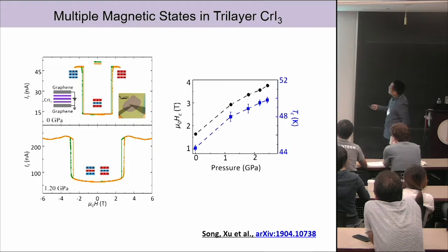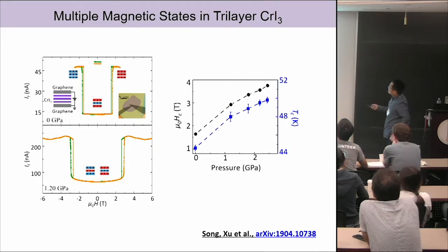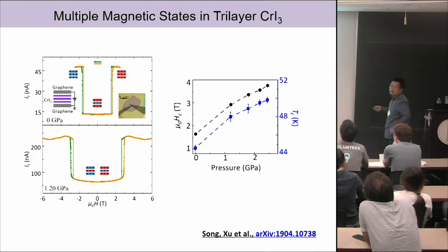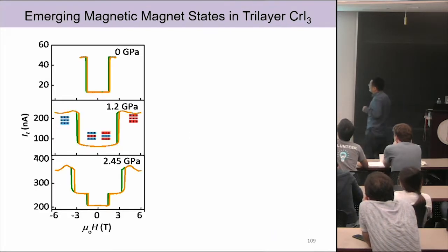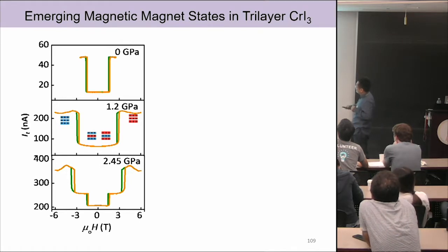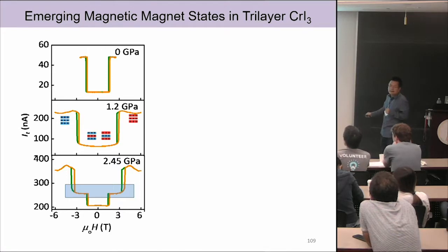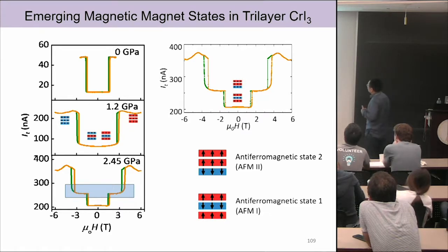So again, in the trilayer, the top one is the tunneling current measurement without pressure, the bottom is with pressure. And we can see the critical field for the spin flip transition increases just as we saw in a bilayer. Everything is consistent. But what's interesting is that at the higher pressures, I observe intermediate states showing up. This means there are new magnetic states appearing at the higher pressures. And this new state is coming from another antiferromagnetic state.